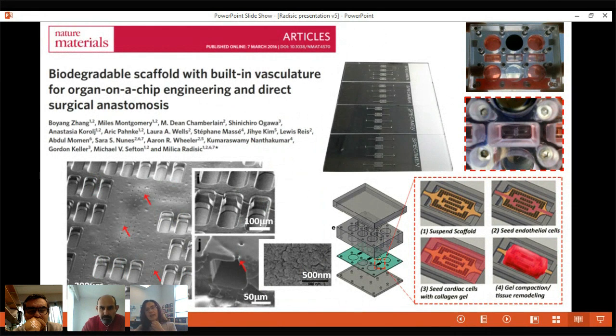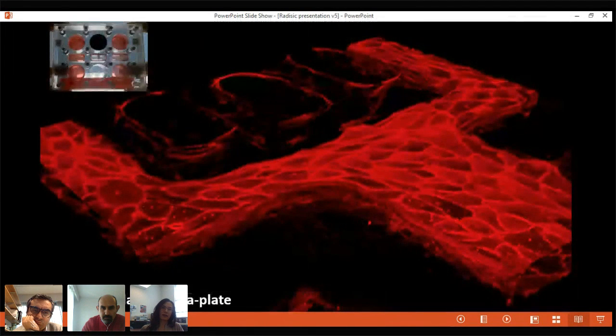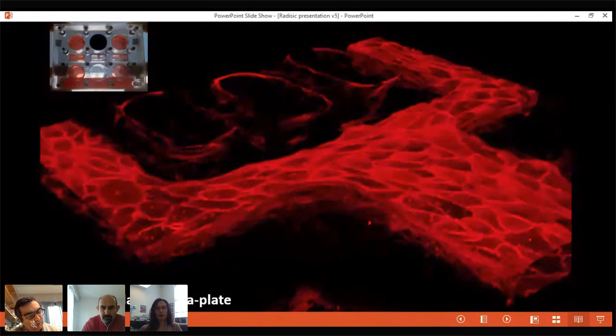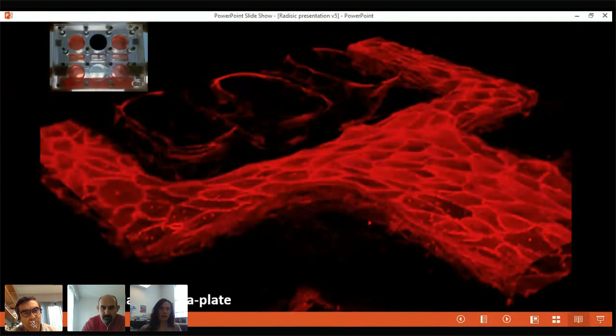The next step is sealing of the cells using a hydrogel around the scaffold, and then if you wait for several days, the process that includes this cell gel compaction will lead to formation of stable tissues. I should also mention that these polymers here are usually gelatin coated to further support cell adhesion. And you can see that it is possible to create nicely confluent endothelium on these inner lumens, and that even the corners are well covered.